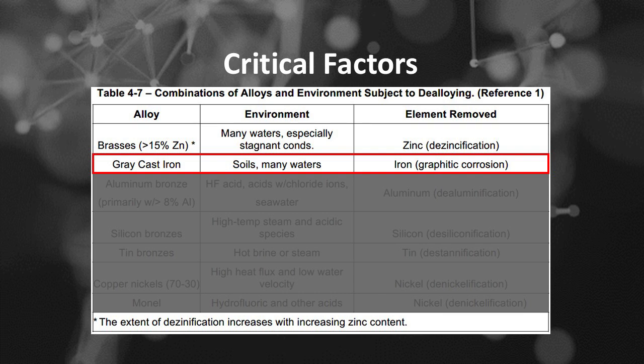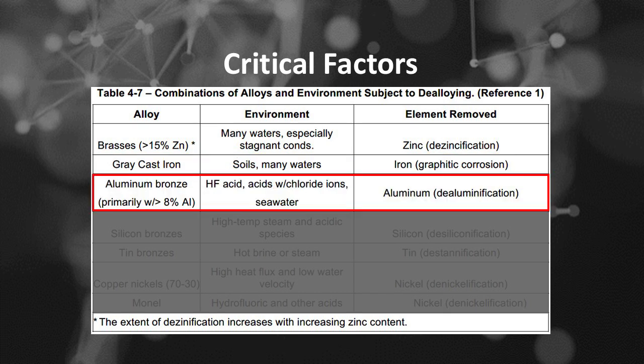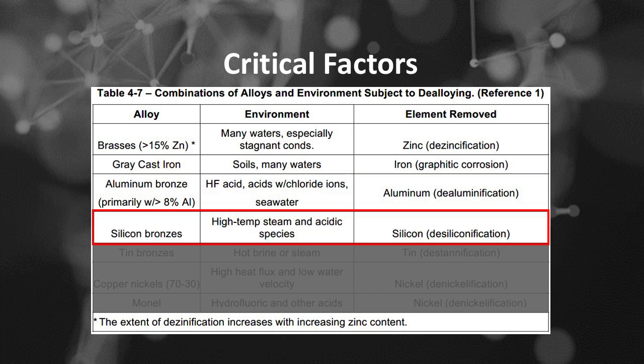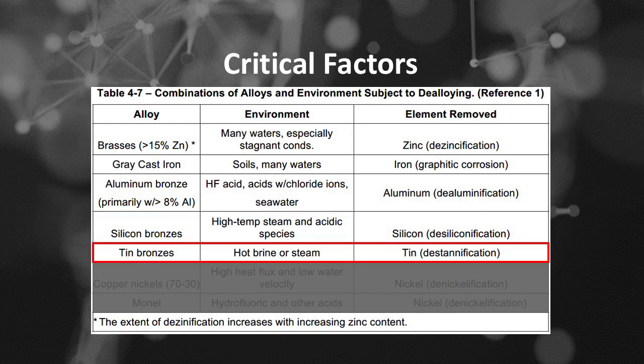corrosion. If alloy is aluminum bronze, primarily with greater than 8% Al, and if environment is HF acid, acids with chloride ions, seawater, then element removed is aluminum, or dealuminification. If alloy is silicon bronzes, and if environment is high temp steam and acidic species, then element removed is silicon, or desiliconification.